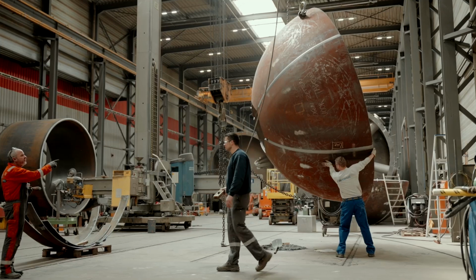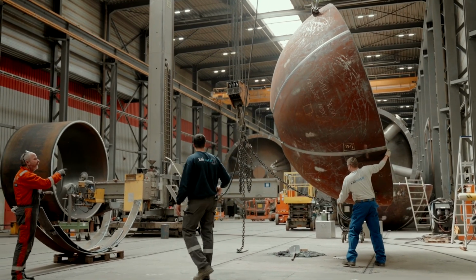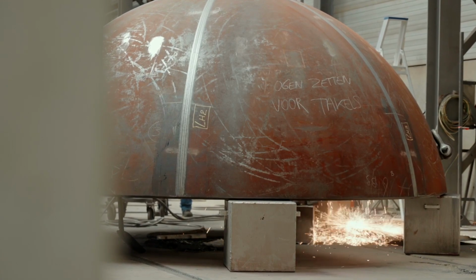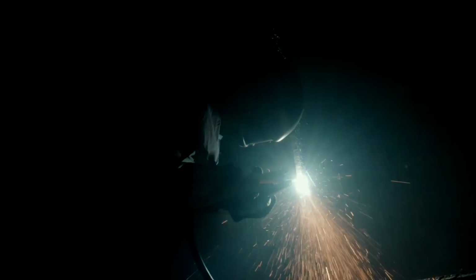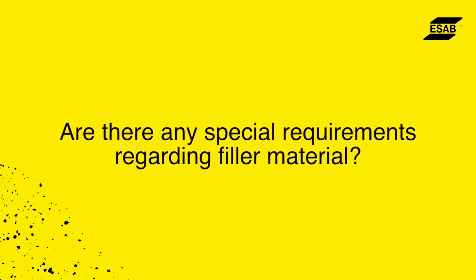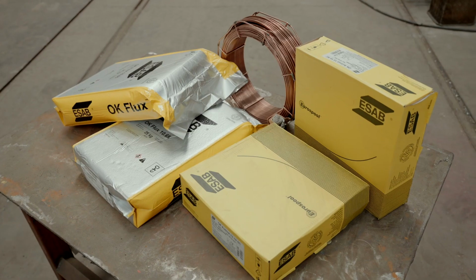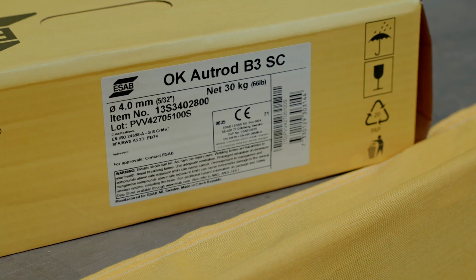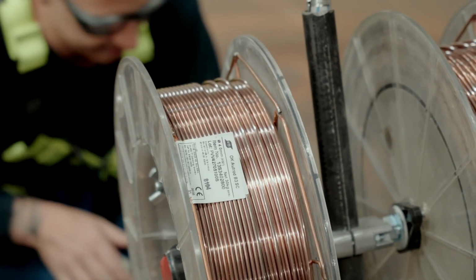The tough requirements according to API 934A were very demanding and challenging. We need to get an impact test values at 55 joules at minus 29 degrees Celsius. The X-bar shall be less than 15. The step cooling test was required and the maximum hardness was 235 Vickers. The filler metal needed to be 3.2 chemical and also mechanical certified, including a step cooling. The OK Autrod B3 SC was designed especially for this.